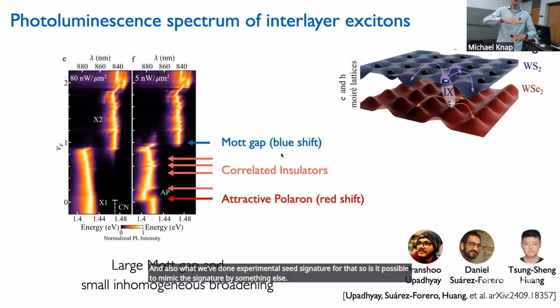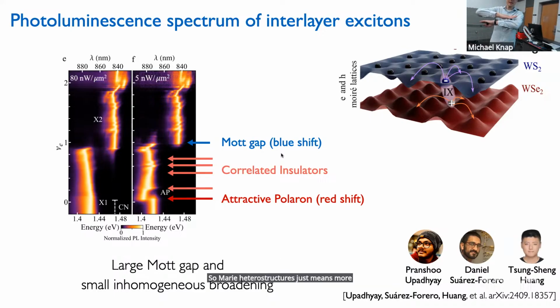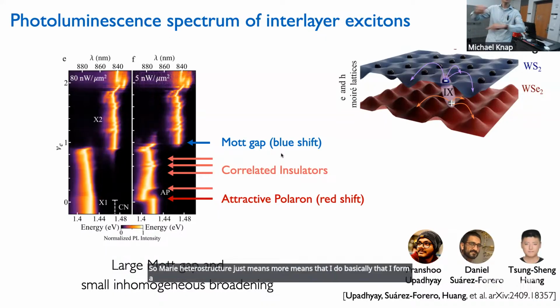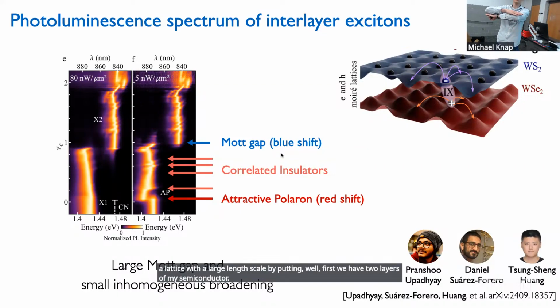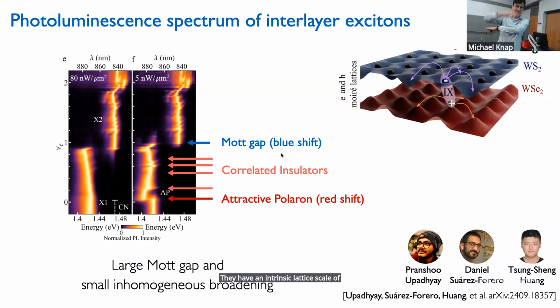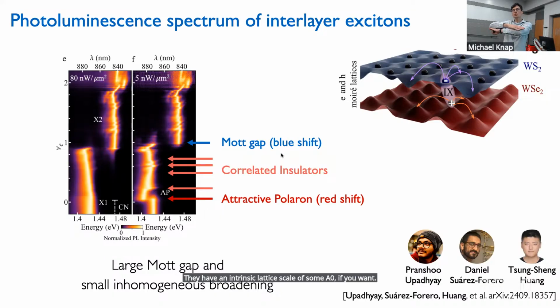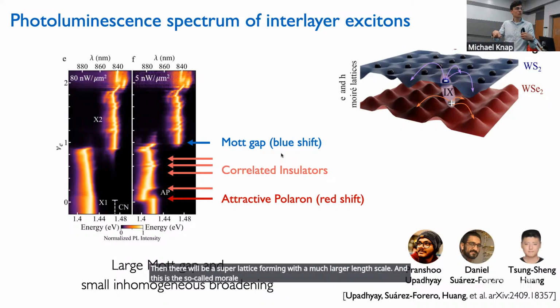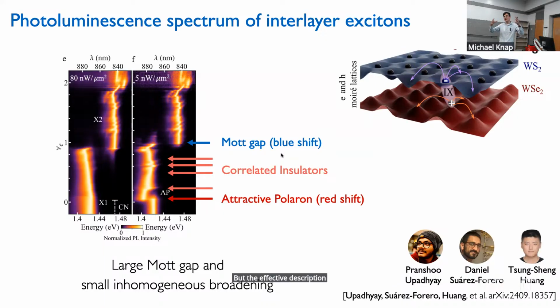So Moiré heterostructure just means that I form a lattice with a larger length scale by putting, well, first we have 2 layers of my semiconductor. They have an intrinsic lattice scale of some a0, if you want. When I put 2 materials on top of each other and twist them a little bit, then there will be a superlattice forming with a much larger length scale, and this is the so-called Moiré lattice. And the effective description, I will go more into the detailed modeling of the systems later, but the effective description is then that I have a triangular lattice system with a relatively large unit cell at my disposal.